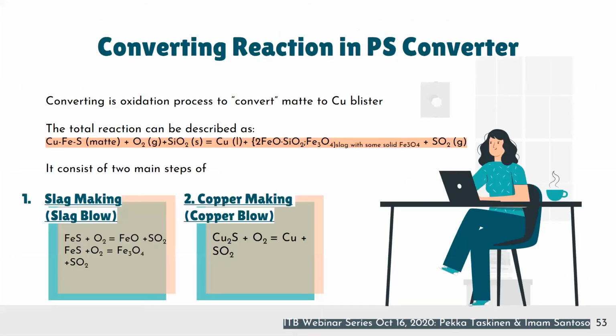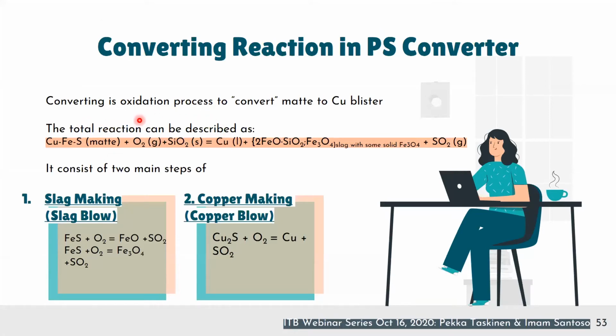And then, okay, next, what are the reactions? What happens in the converting process? In converting, we want to convert matte to become copper. So this is matte. We want to change it to copper by introducing oxygen and also silica as a flux. And there are two main reactions. The first reaction is oxygen reacting with iron, producing slag. And the second reaction is oxygen reacting with copper sulfide, producing copper and sulfur dioxide gas.